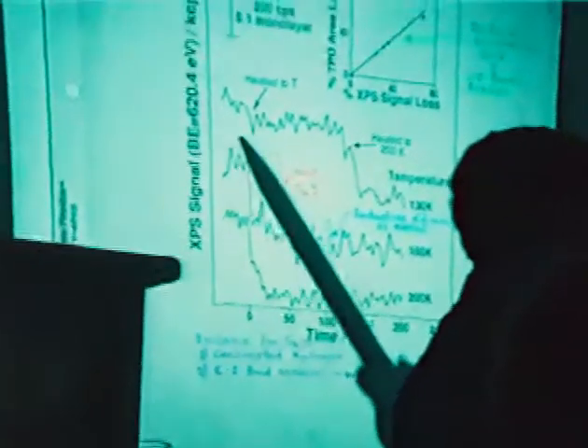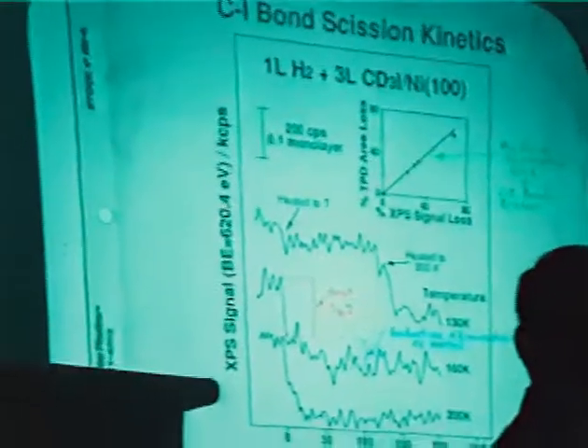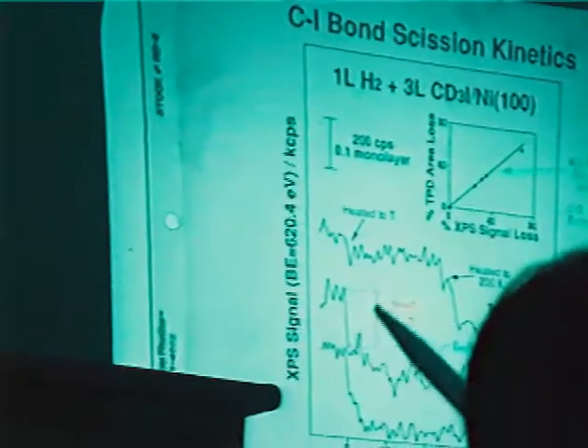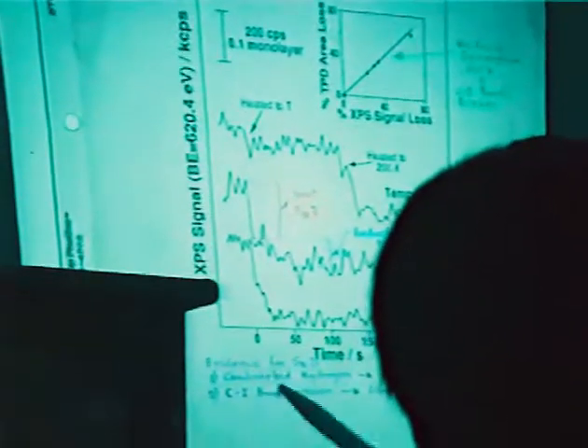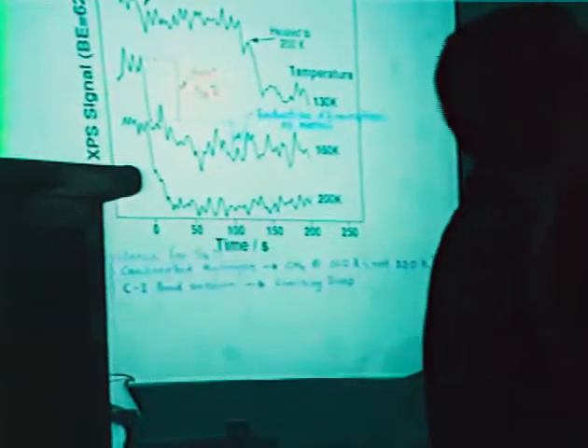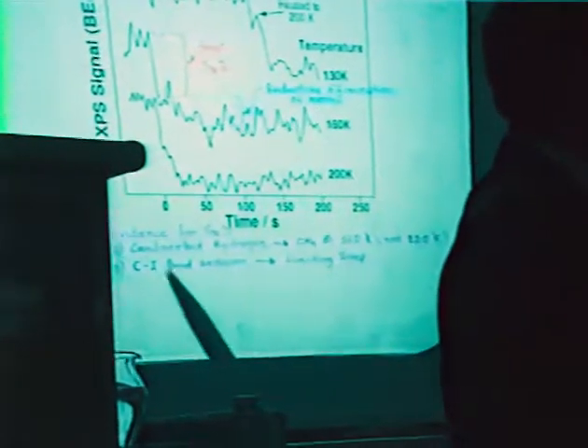The amount of XPS loss suddenly down here versus the TPD area. And so you get to see that there are two steps here. One very fast in which the carbon-iodine bond breaks at the same time as when you form methane, and then the regular step where methyl iodide dissociates slowly, but then methane forms from methyl groups and not from methyl iodide. So this first step is a new step which we think involves methyl iodide by itself, without dissociation. And we propose an SN2 mechanism. These are summarizing every piece of evidence that we have for it. This pathway only takes place in the presence of co-adsorbed hydrogen, and it takes place at very low temperatures, below the temperatures needed to break the carbon-iodine bond by itself.